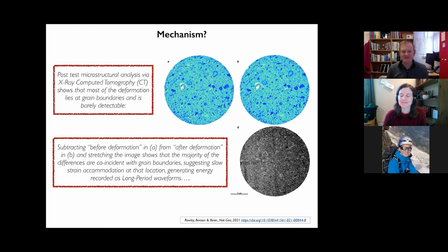So typically an experiment can take an hour, and then you need to do one that takes a day to go to 10 to the 6 strain rate, and then to go to 10 to the 7 it's going to take a week. Keeping a machine running for a week consistently without going wrong is already difficult, and then you go to a month and you move to the creep regime, and this was a problem that we found. So we would like to have done more experiments, but we didn't manage it, I'm afraid.